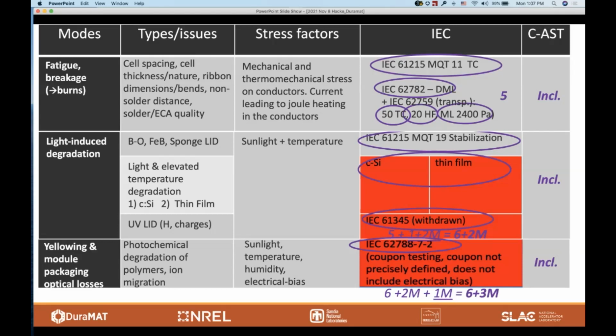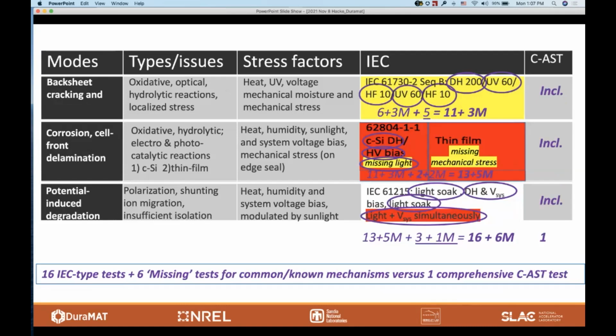In thin films, for example, we're just creating a standard now for getting good light-induced degradation. For yellowing, module packaging and optical losses, we have a general test in 62788-7-2, but it doesn't include electrical bias, and the coupon is not precisely defined. For backsheet cracking, there's a test for it. DuPont has been a pioneer of that, but it involves a number of different stress sequences. And if you add it all up, we have 11 existing IEC tests plus 3 missing tests.